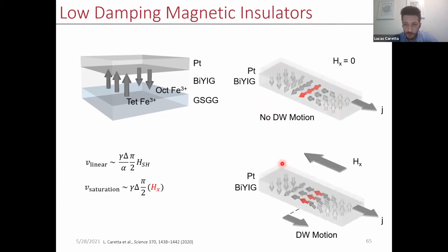So what we did in this experiment is once again go to our in-plane field. We apply an in-plane field to cant this domain wall from a Bloch configuration to a Néel configuration. And the amount of field it takes to do this is actually not very high. The domain wall anisotropy is very, very low. It's at least one order of magnitude lower than the anisotropy of the bulk of the film.